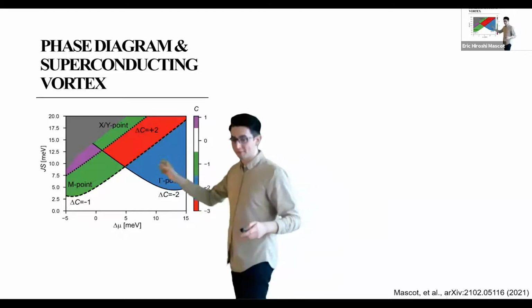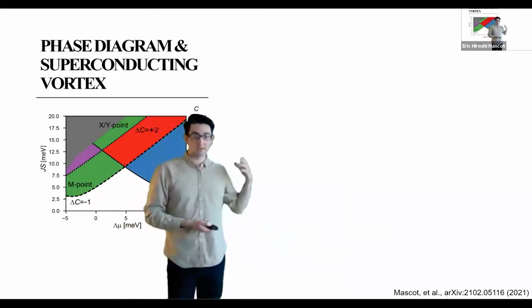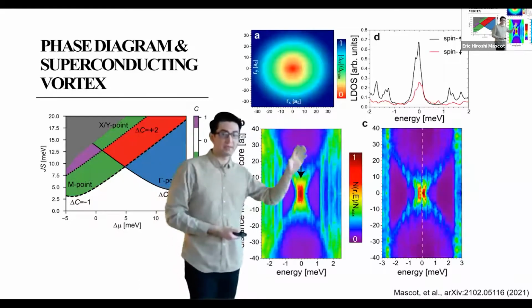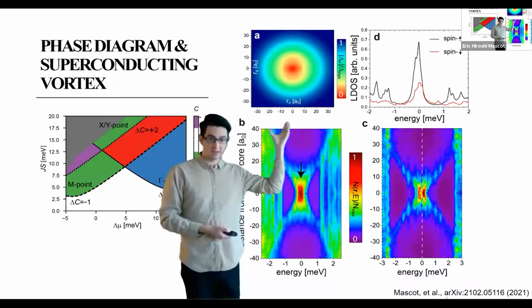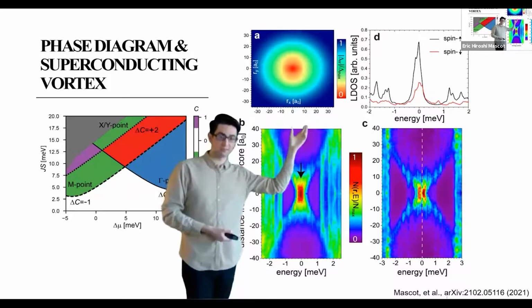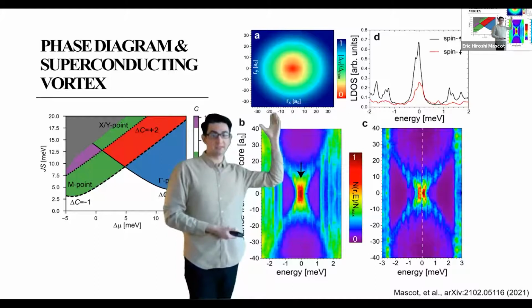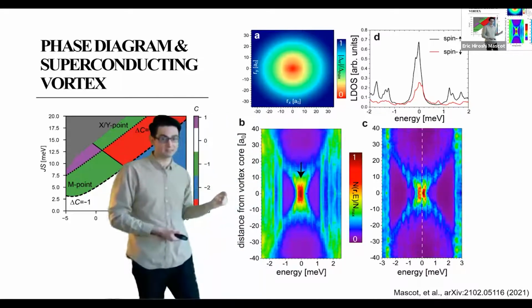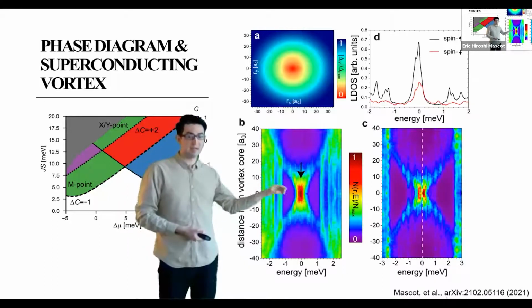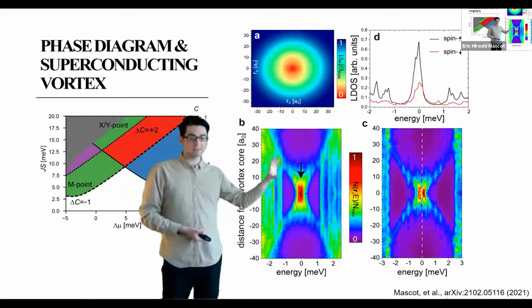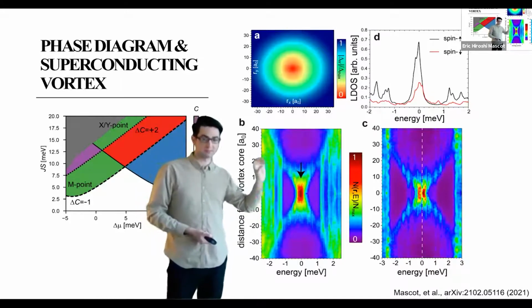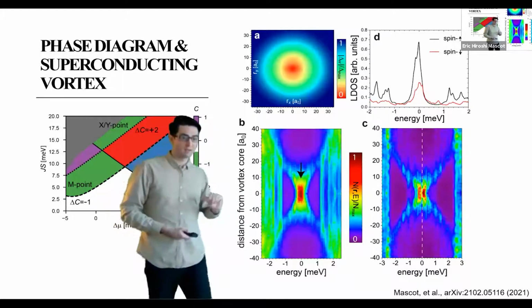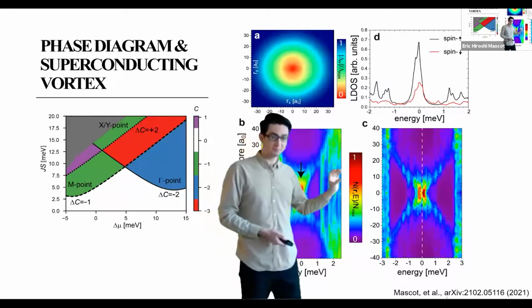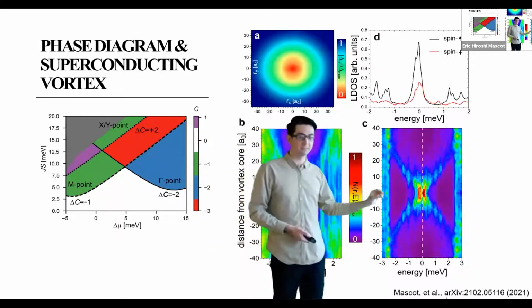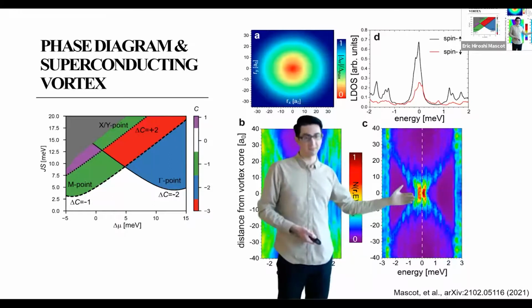And if we go into a topological phase, we compare it to the experiment with the vortices. Here we added a magnetic field and self-consistently calculated a superconducting vortex. And we can then calculate the local density of states inside that vortex. And in the core, we have a zero energy state. And then we also have these other states. These are trivial vortex bound states that are non-zero energy. However, if you look at a topologically trivial case, we don't see a zero energy state. We see states that are split from zero.